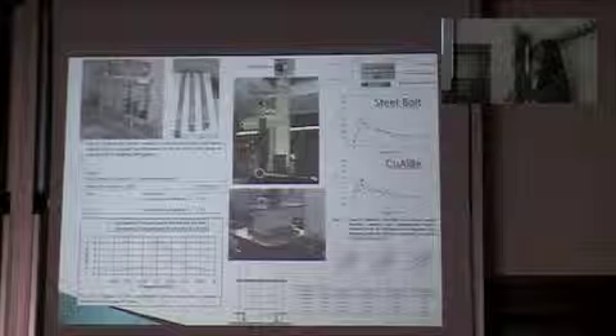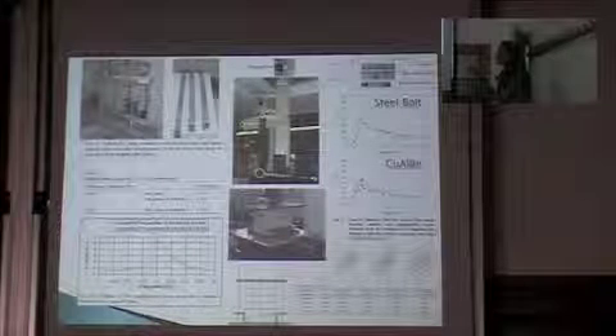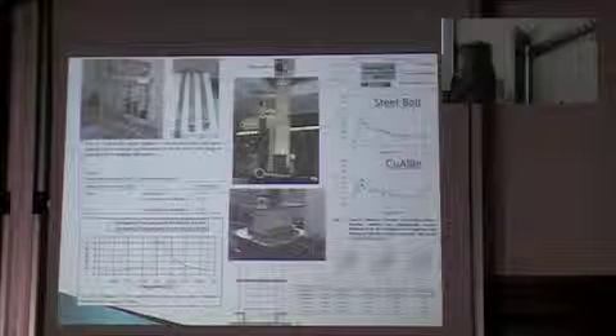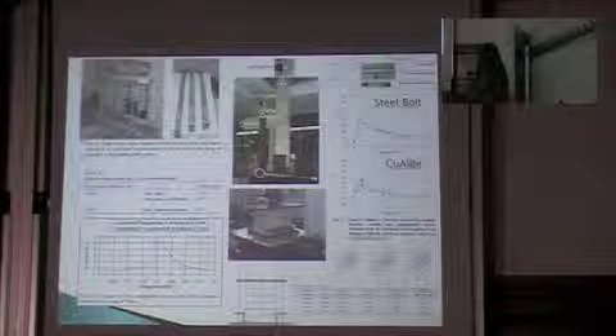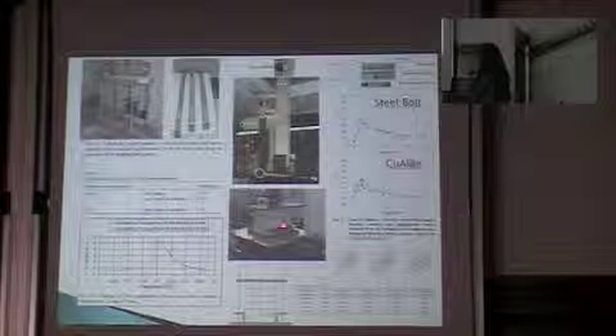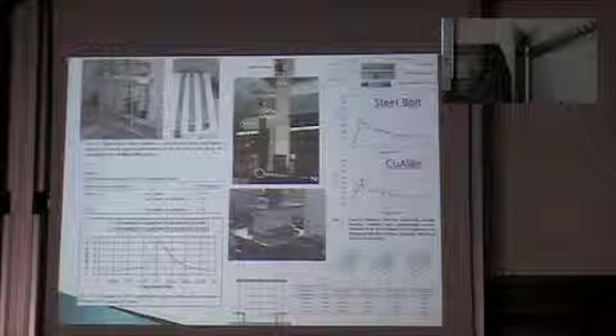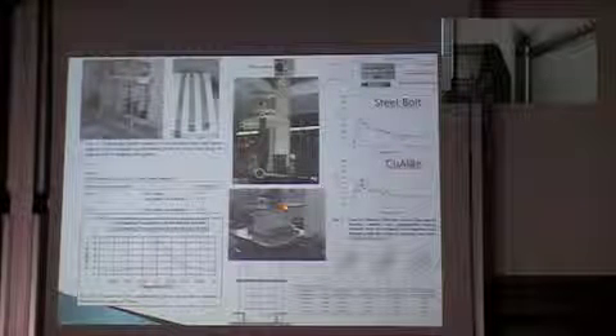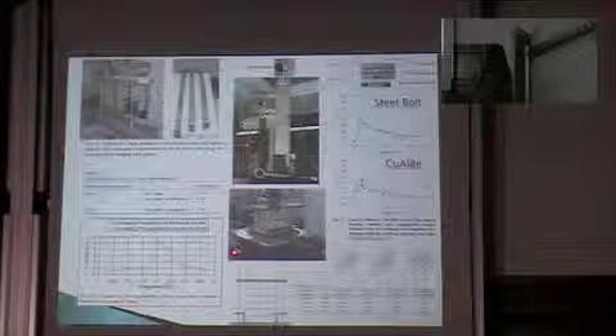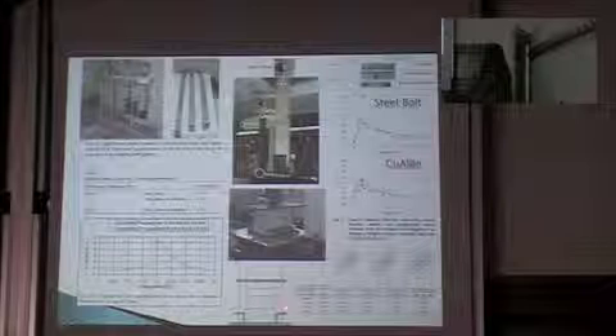So here we have nonlinearities that are geometrically introduced by the fact that there is no connectivity between the bricks. And we repeated the shaking table test on the loosened bricks, which are held together only by the compressive force of the pressure of the plate at top. And then we introduce the shape memory alloy wires between the top and the bottom plates. And we analyze the results also from a numerical point of view.